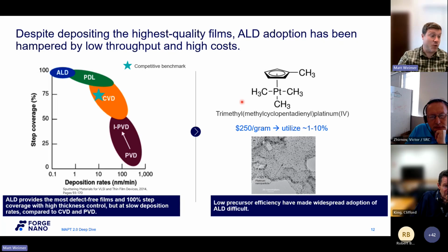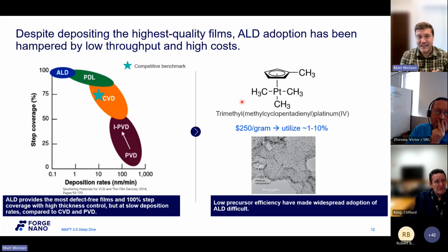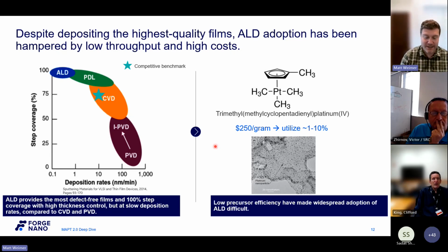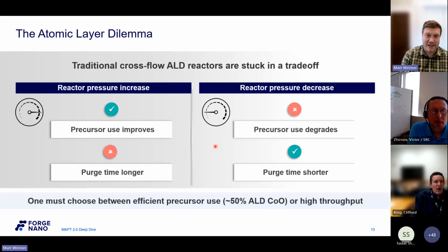The second thing is ALD tends to waste a lot of precursor. I think I saw a press release from ASM saying they have a metal oxide ALD process that was up to 50% efficient in precursor use. That means you're pumping 50% of your precursor down the drain. Still not very good. It gets even worse when you talk about metal ALD. So here's a typical precursor for platinum metal ALD. It's quite expensive, and normally you utilize maybe 10% if you have a really good process. So if you're flushing $250 per gram down the pump, that's not a very production-worthy process. So again, these are the most well-known. I'm not really blowing anybody's mind here.